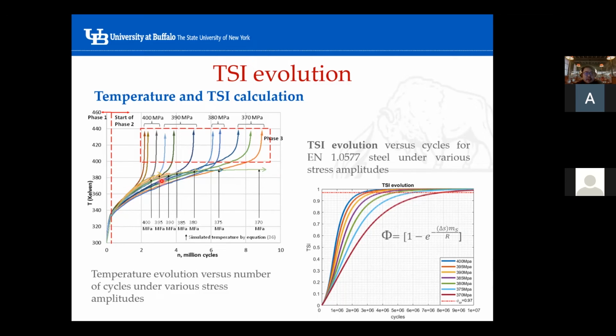We can see that the simulated temperature matches the experimental data in phase 1 quite well, with a little difference in phase 2, but it cannot capture phase 3, because in our thermomechanical equation we are not including the evolution of the cracks, so of course our equation cannot simulate phase 3.